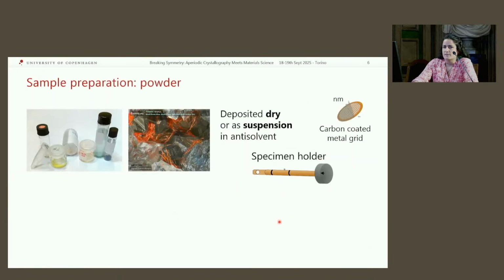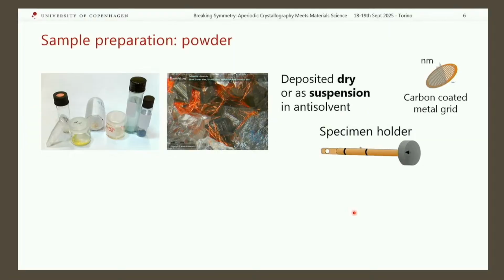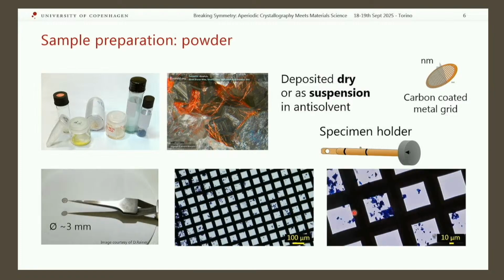So how do we prepare a thin sample? Well, we have just seen that in some cases we have a solid sample that is already made by small particles, so the grains of our powder sample can be less than 1 micron. And then it's very easy to prepare the sample. We can just disperse it on a very thin support grid. You can see it looks like everything is very small.